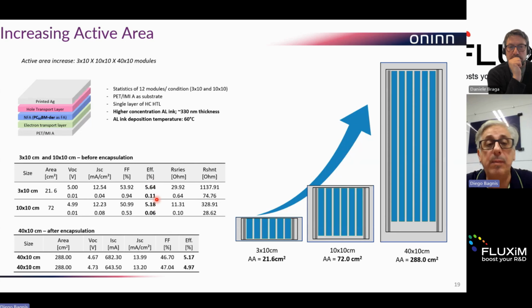This is pretty expected, especially connected to the fill factor. You see that the other parameters are more or less the same, but the fill factor is one of the parameters that I mentioned in the beginning that drops in the scale-up. And if we take the 40x10 after the encapsulation, we see that there is still one small drop, but this drop is really small, so in this kind of formulation, the increase of the dimension is not a big issue. This means that what we achieve for the small mini module, we are able to achieve slightly less, but with similar results, with the bigger module.